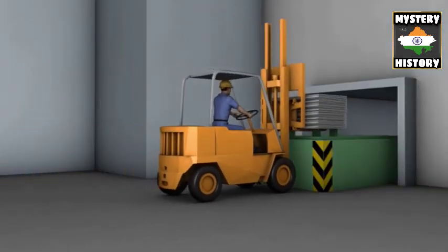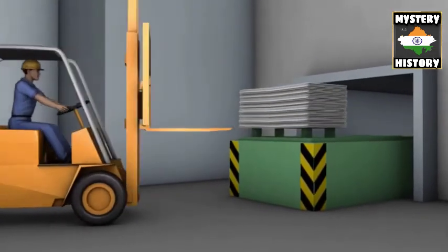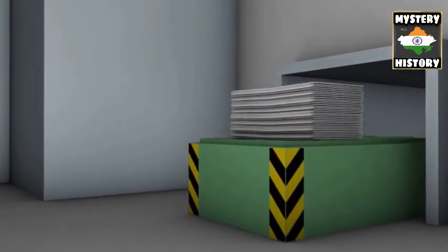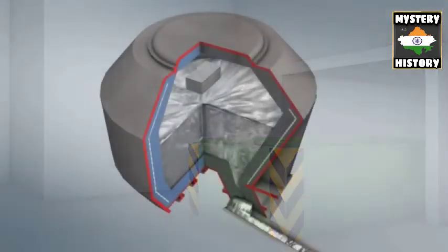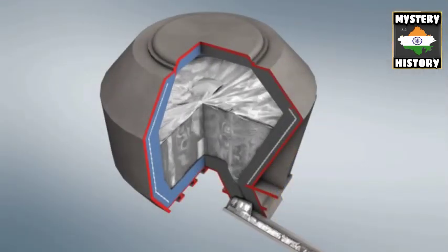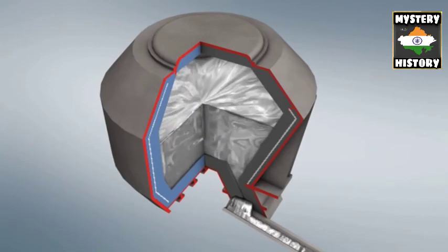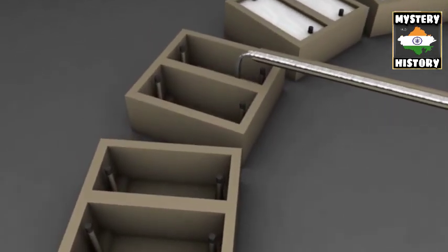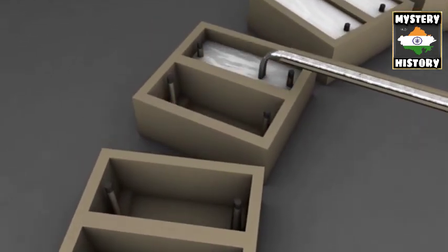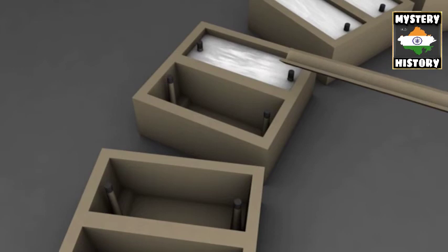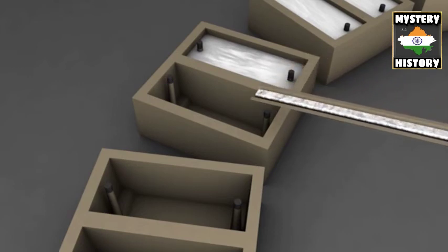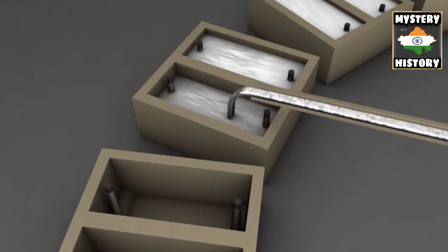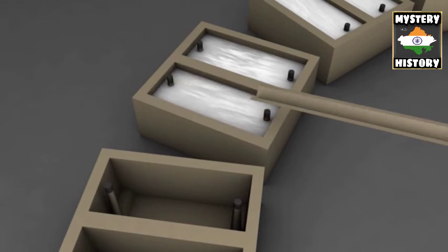The electro-deposited zinc from the electrolysis step is melted at over 420 degrees Celsius in induction furnaces and cast into slabs or jumbos weighing from 1 to 6 tons, or into special shapes, depending on its use and the needs of the customer. In some cases, small amounts of aluminum or other metals are added to meet customer requirements. Strict quality controls are followed during the casting process, including the regulation of returning scrap from the casting process to the melting furnace.